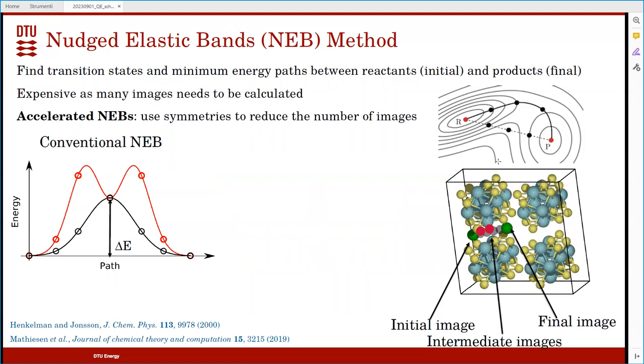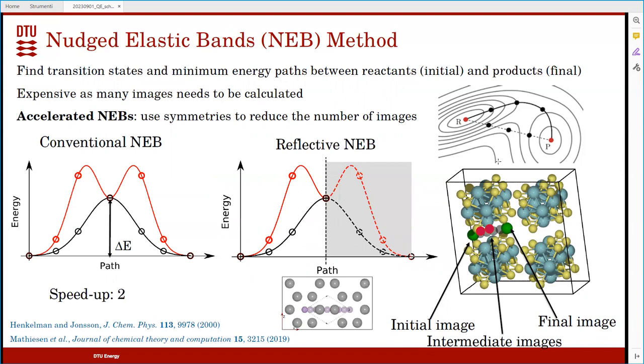But then there are different ways to accelerate this. There is machine learning, there are different ways. What we do is just use symmetry. Most of the barriers have a mirror symmetry in the middle, right? So if we can calculate half of it and then mirror it, we already save almost a factor of two. And this is what we do here. We have the so-called reflective NEB, where instead of doing the full path, we do half of it and then we double it up.